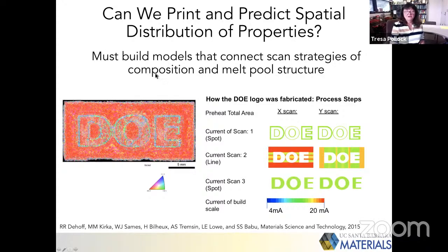Now, as I said a moment ago, what we really must do if we're going to print things for critical applications in aerospace is really control structure to a high degree. And so I show here a print. This is the work of Dehoff and Kirka at Oak Ridge. They did this very clever study a number of years back now, but their point was to show that they could control the columnar to equiaxed transition during printing, and in doing that, be able to print a DOE into a laser powder bed process. Now you'll see that this is not perfectly well printed. And so the question is, can we really control this structure to an even greater degree?